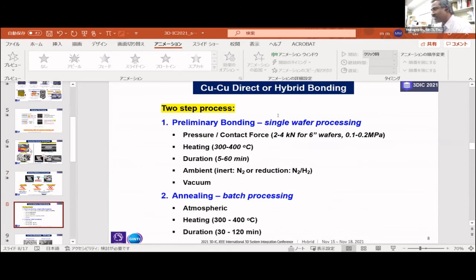These are some of the typical steps. In copper-copper direct or hybrid bonding, the preliminary bonding is single wafer processing, whereas afterwards, to improve your copper diffusion or bonding strength, you have to go for annealing. You can do this by either single or batch processing. Of course, the temperature and time duration depend upon different conditions.